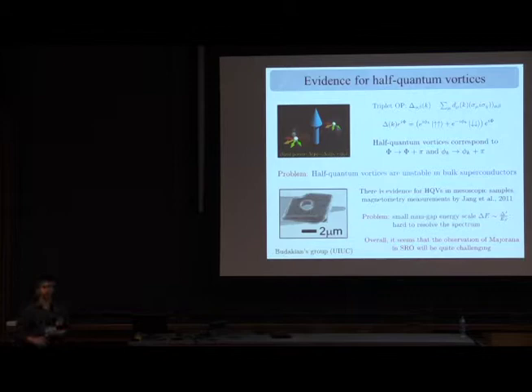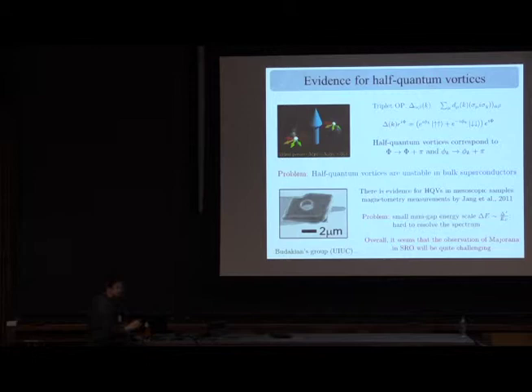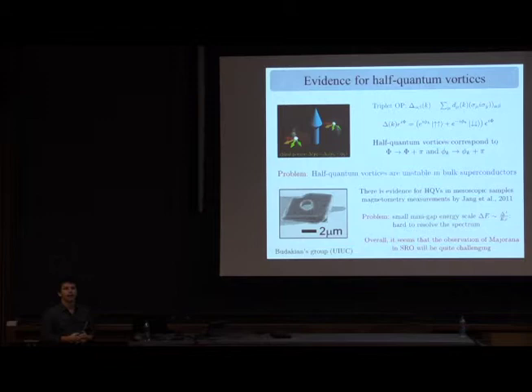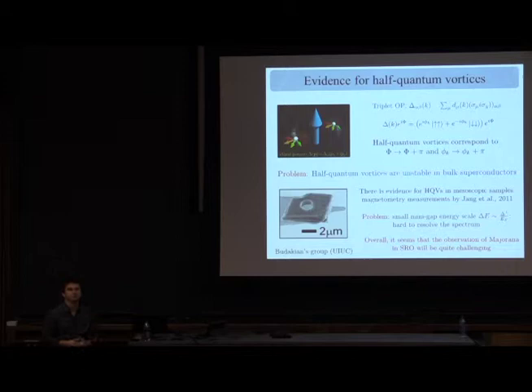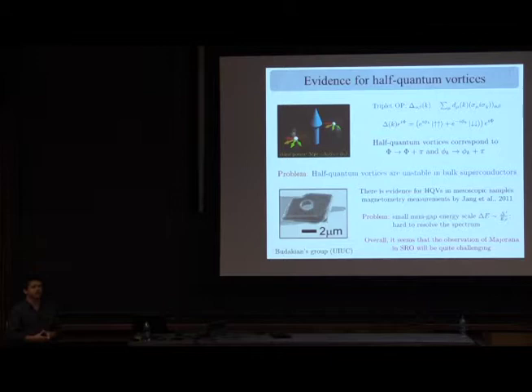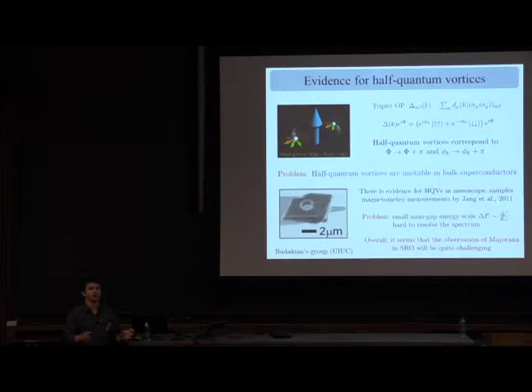Q: How is a vortex in a D-wave superconductor different? A: D-wave superconductors still have a half-quantum vortex possibility, but D-wave has nodes — instead of localized in-gap states as in S-wave or P+iP, you have extended states along certain symmetry axes. Also in D-wave, because TC is large, vortices are very small and behave more like quantum objects, whereas in S-wave superconductors vortices are almost classical because the coherence length is large.